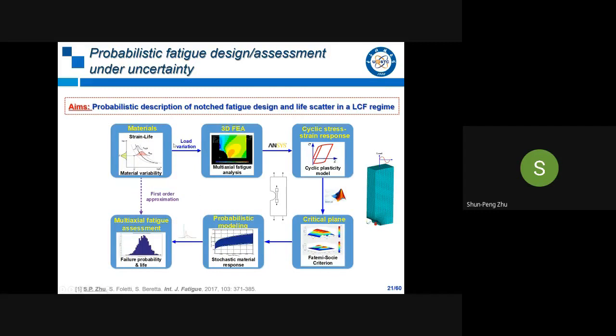And here is the detailed procedure or steps. First, we try to quantify the material reliability. Then with this, we include the load variation with this notch specimen. This is a half symmetry notch specimen, under uniaxial tensile loading, but for the notch part, actually the multi-axial stress states. For this part, we transfer the material variation and load variation to the stress and strain response variation, and then to the damage parameter. Here we choose the Fatemi-Socie equivalent shear strain parameter. Finally, we output the failure probability and the life.